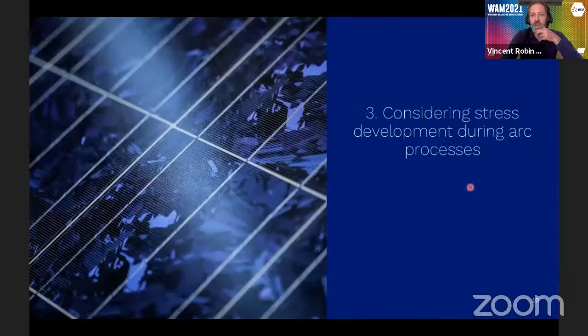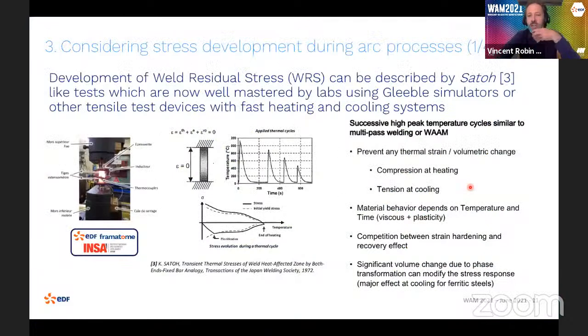Let's go now to a short description of the way we validate our model in terms of mechanical behavior. We mainly base our approach on Satoh-like tests. Maybe some of you know this test. It's well known for welding applications, and this test is really interesting to reproduce the behavior of the material during successive peak temperature cycles that can be observed in the component during multipass welding or 3D printing.